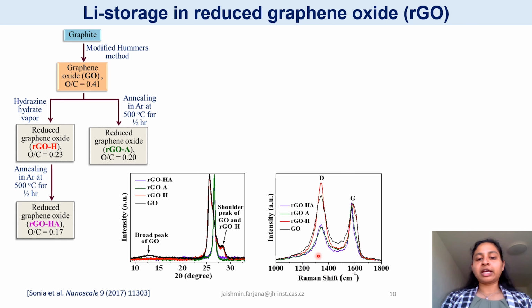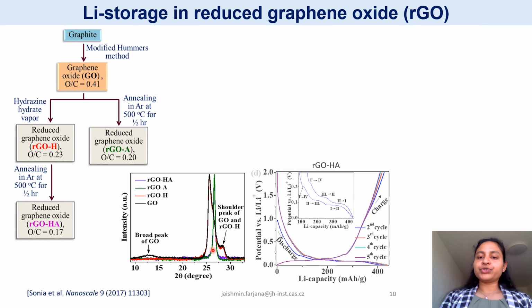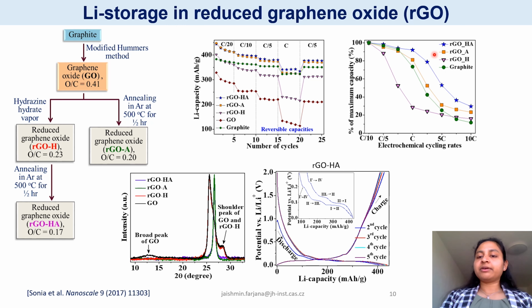But we have seen that if we can optimize the process parameters, then even for this reduced graphene oxide, it is possible to have fewer defects and very well ordered RGOs, which can give rise to a potential profile very similar to that of graphite. That means proper classical intercalation of lithium in the reduced graphene oxide also, but still having a higher capacity and higher rate capability for these RGOs.